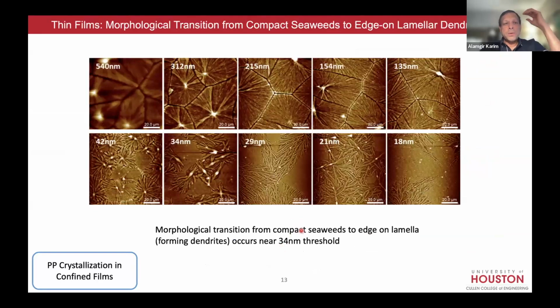Okay, now what happens to the morphology of these films as we have different thicknesses? And this is just showing you 540. This is now late stage crystallization behavior. They initially start out by forming spherical spherulites around these nucleation points. But the spherulites grow and they impinge on each other and they form these kind of Voronoi tessellation-like patterns. The 312 shows you very clearly. These are kind of pentagonal, hexagonal, and all kinds of interesting geometry. Essentially, you have crystal grain boundaries at these interfaces. As you reduce the film thickness, they get larger. It's not really larger, but they get more defined.